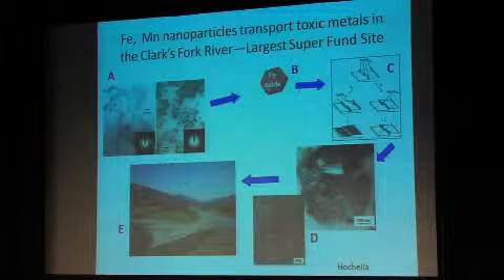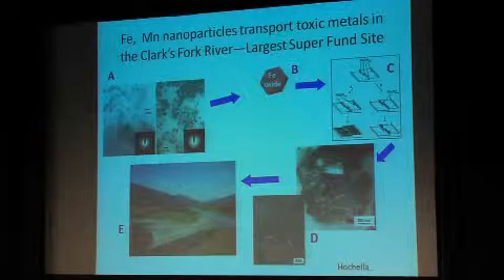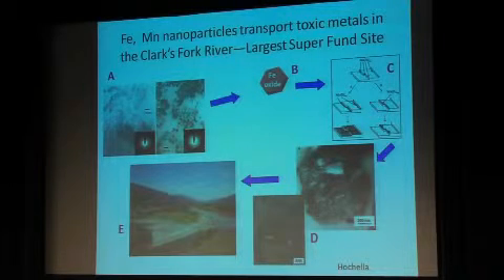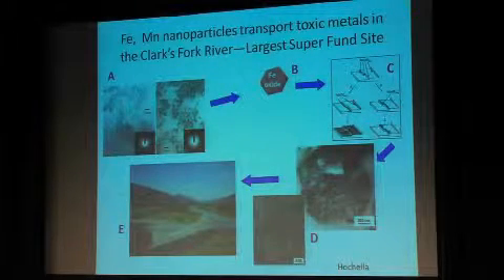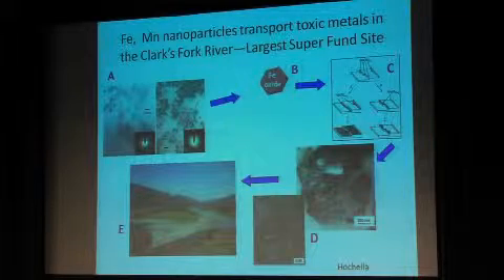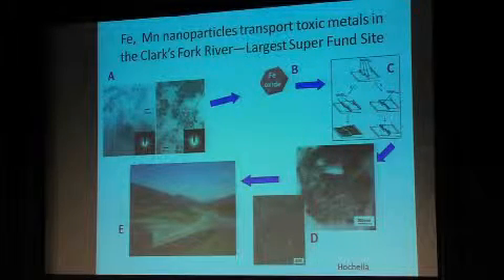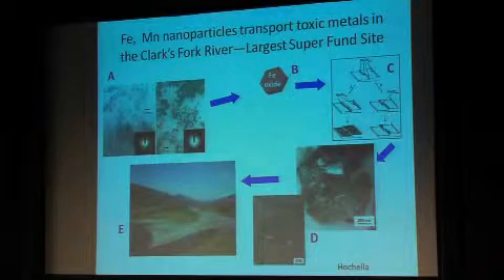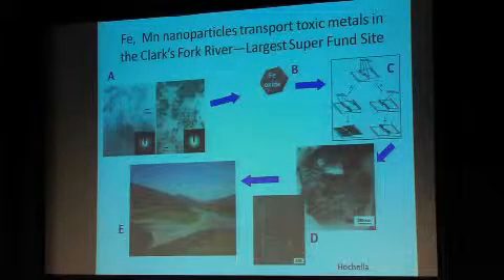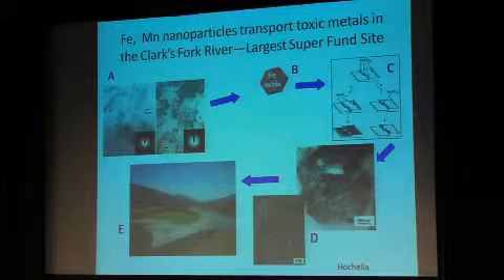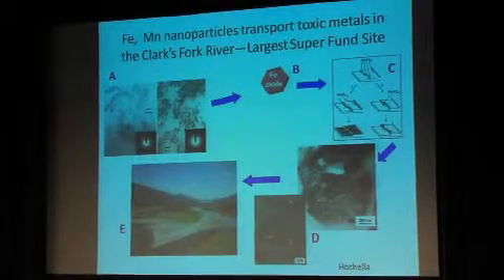And those nanoparticles have very high surface area. I'm going to talk about why surface area matters in this, and they carry a lot of the pollutants. And because they're nanoparticles, they react very quickly, and that means the pollutants attached to them can change very quickly. For example, you can have photocatalyzed reduction of the iron oxides that kicks the toxic metal off, and then at night, or when it gets a little deeper, you can have the opposite process. So you can have very fast reactions when you've got these nanoparticles in high surface areas. So these nanoparticles are really controlling the fate and transport.